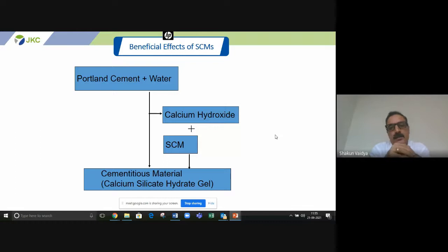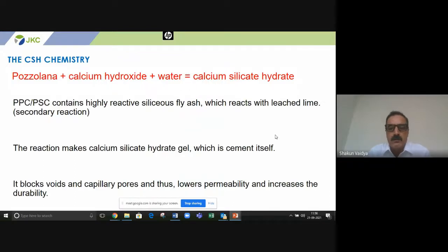So the excess CH reacts with the silica of the SCM, and it produces a byproduct known as calcium silicate hydrate gel. This is the secondary reaction, and this calcium silicate hydrate gel produces a secondary glue, I would say, which further reinforces the concrete. The capillaries are choked, they are more refined with passage of time, and capillaries are absolutely blocked if the environment is conducive. So this is typically how blended cement chemistry works.